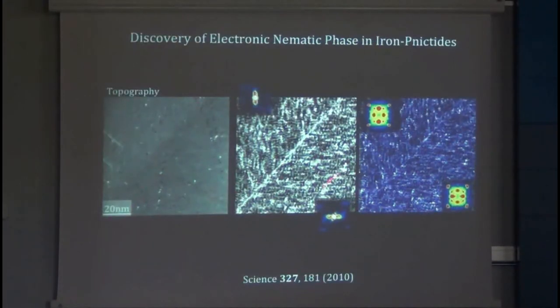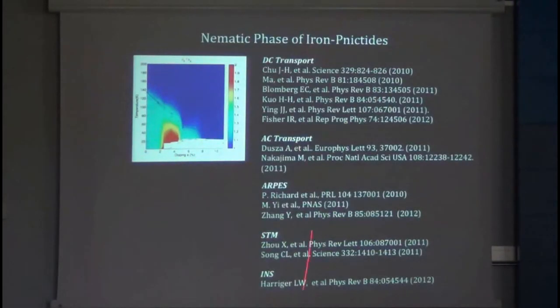It's because at the stage when these experiments were being done, these crystals were not detwinned. All the bulk crystals available in the world were twinned. The two unidirectional orthorhombic domains existed in equal probability in the bulk crystals. So most of the bulk experiments didn't break any rotational symmetry because the crystals were twinned. But if you're looking at the atomic scale, the fact that you have twinning is not a problem. In fact, it's an advantage. Anyway, subsequently, these compounds were detwinned, and then it became perfectly clear that there is a nematic phase in the parent state. Now, a nematic phase is a phase that breaks rotational symmetry, but it does not break translational symmetry. It's not a striped phase. It's a Q equals zero phase breaking rotational but not translational symmetry.